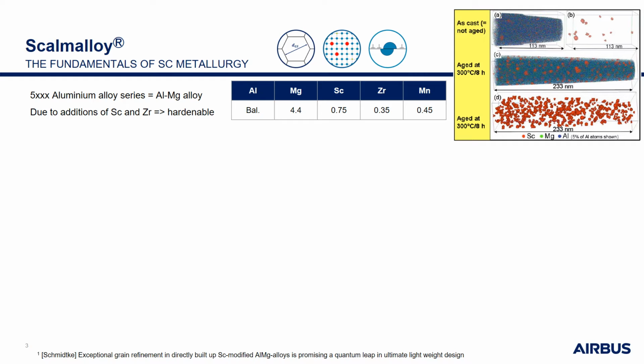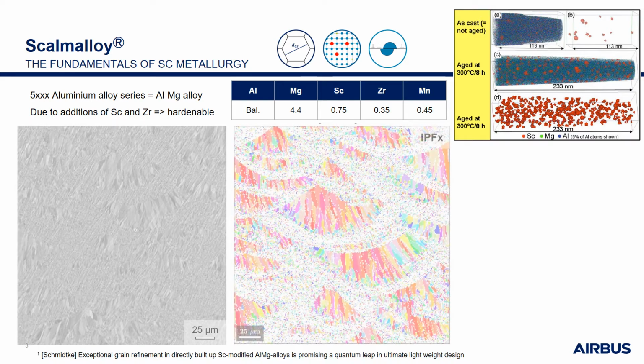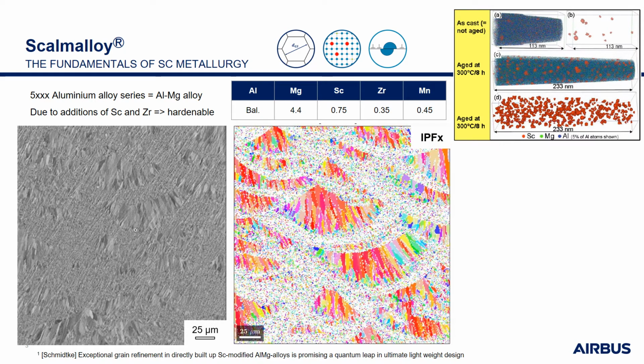Well, the base for Scalmalloy is the 5000 aluminum alloy series, so aluminum magnesium, which are actually not hardenable. But the addition of scandium and zirconium changes everything. On the one hand, we obtain a hardenable alloy, which is hardenable in a single step heat treatment. And on the other hand, we face a bimodal microstructure due to the highly coherent primary precipitates.